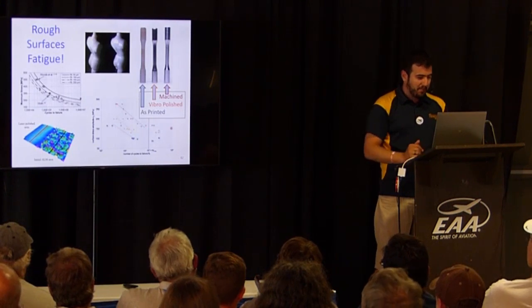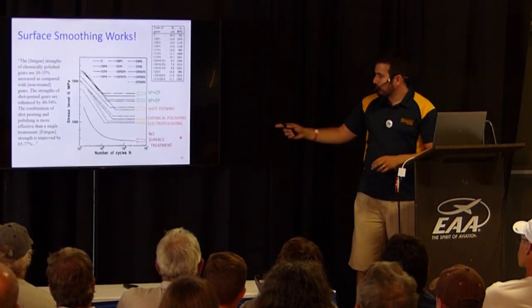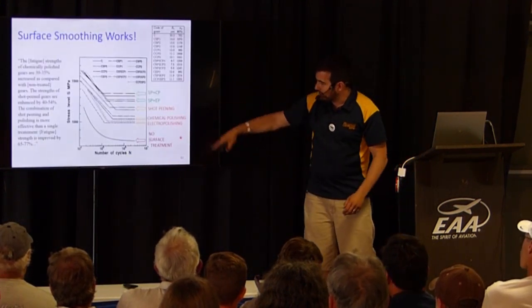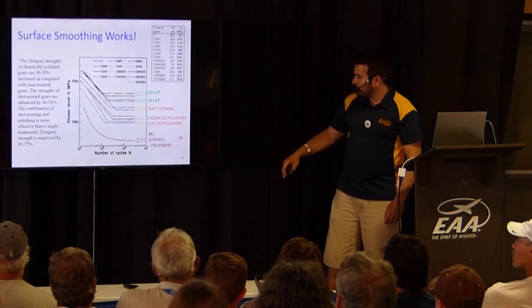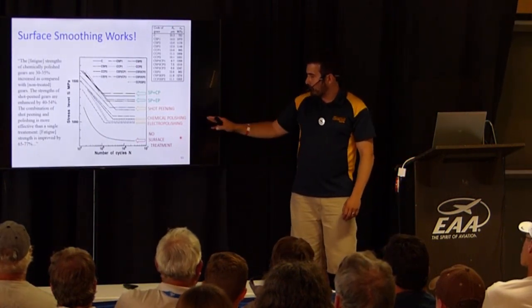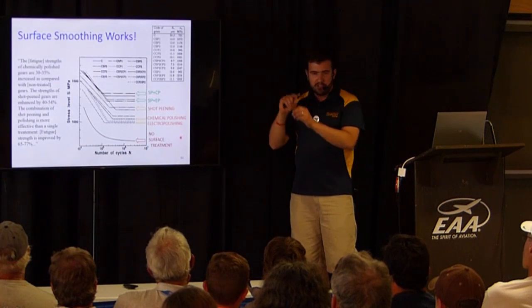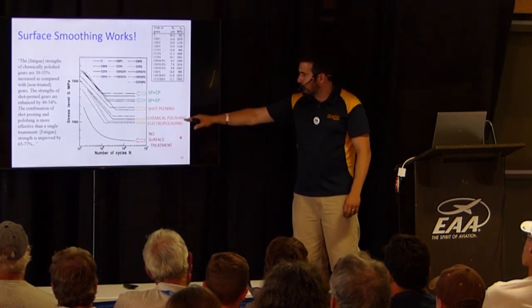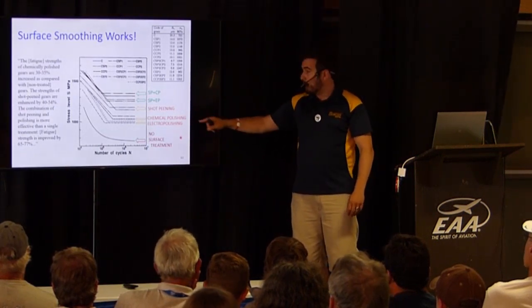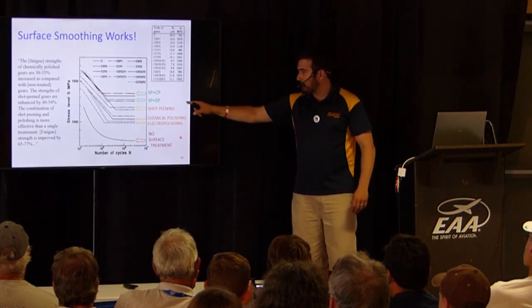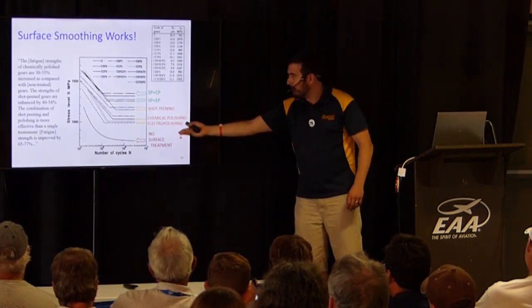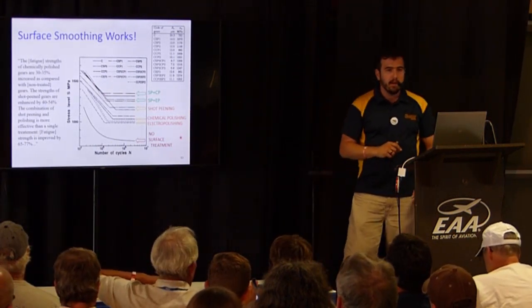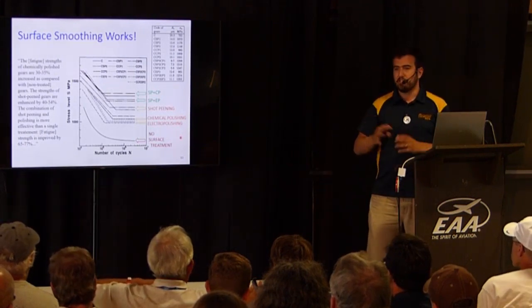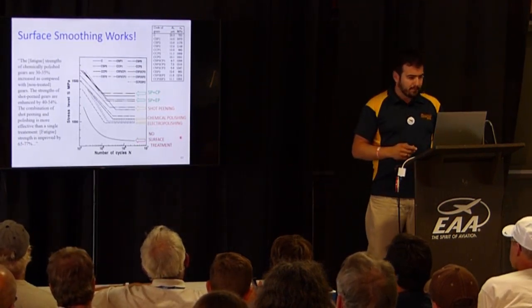And you can actually combine these methods too. So for example, here's one where with no surface treatment, you get that sintered one all the way at the bottom, which is terrible. If you do electropolishing or chemical polishing or shot peening, where you shoot little beads at it basically, each one improves a little bit. And then if you do multiple of these things, if you do electropolishing and shot peening, or chemical polishing and shot peening, it gets even better. So these things actually work, which is kind of cool. Yeah, so there's a lot of research going on into this kind of thing.